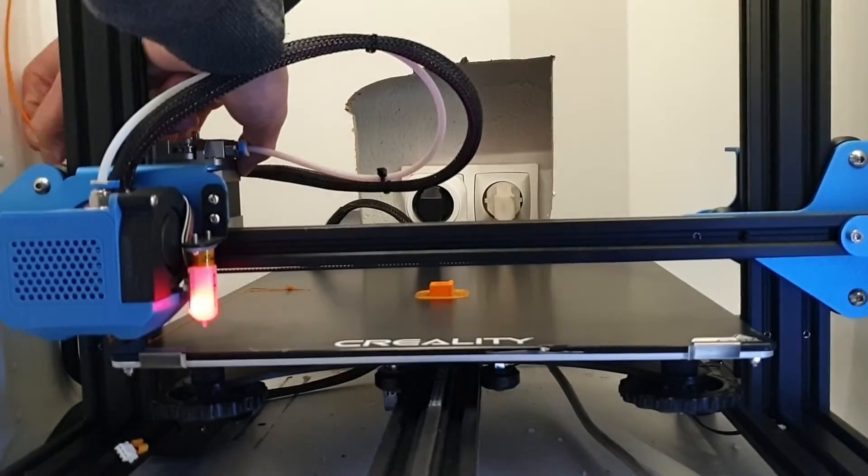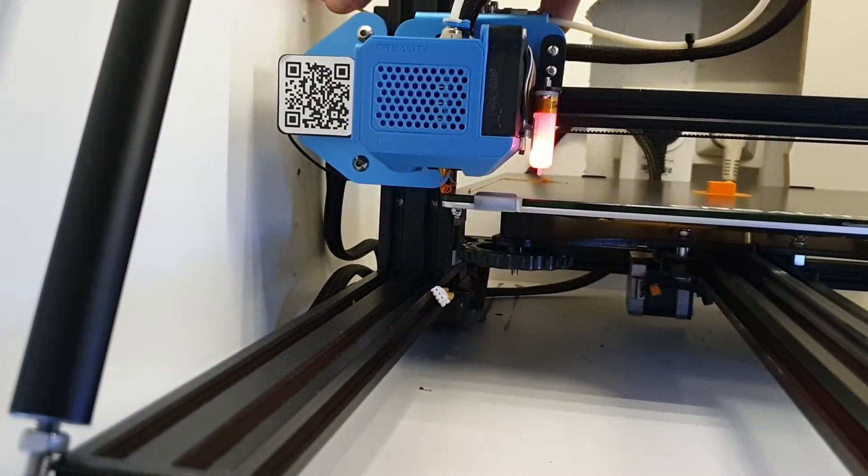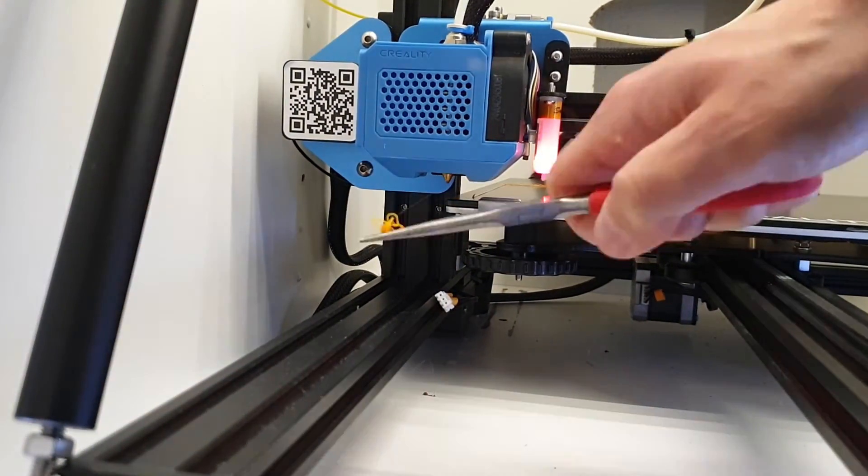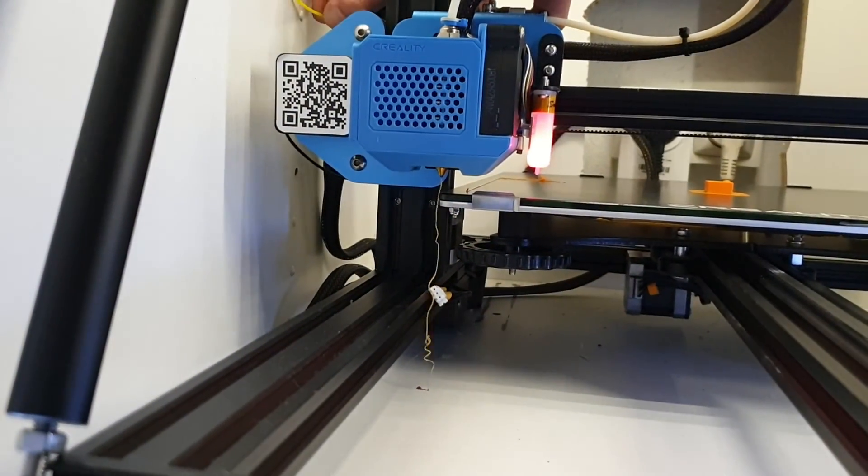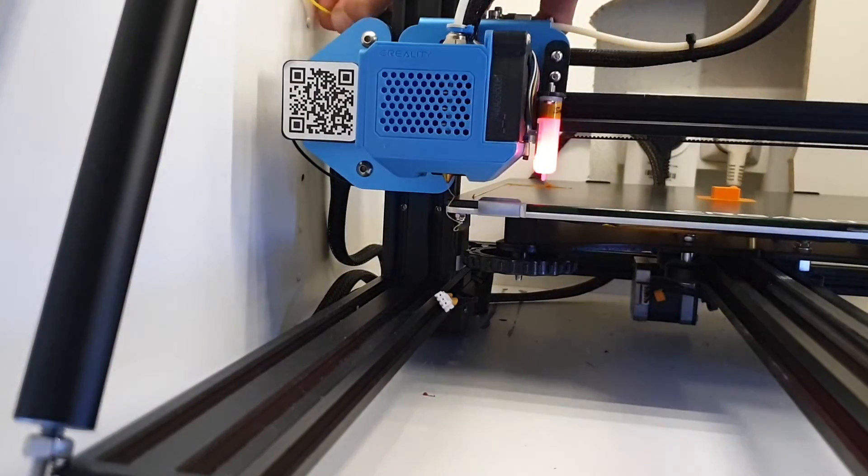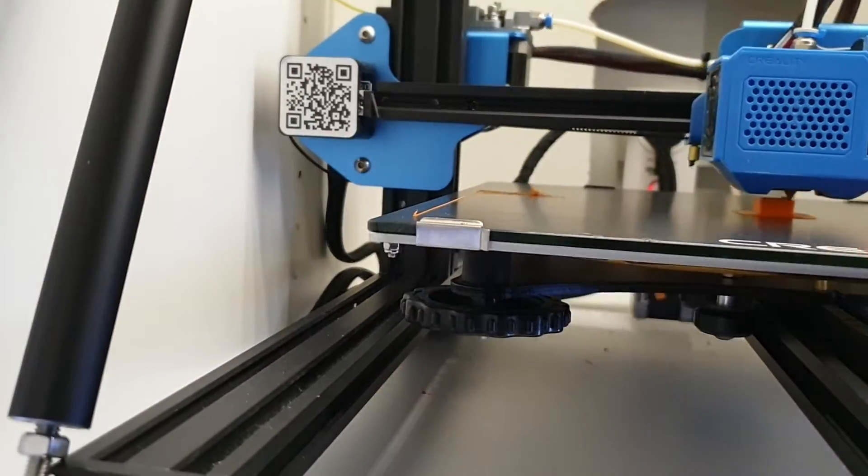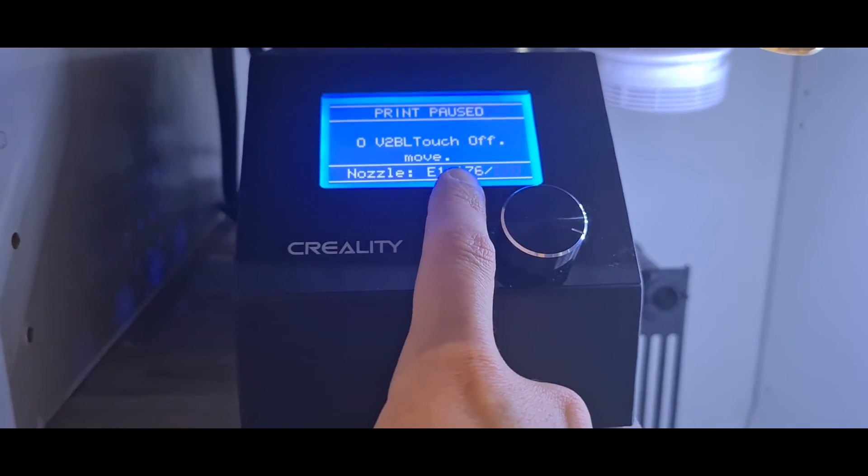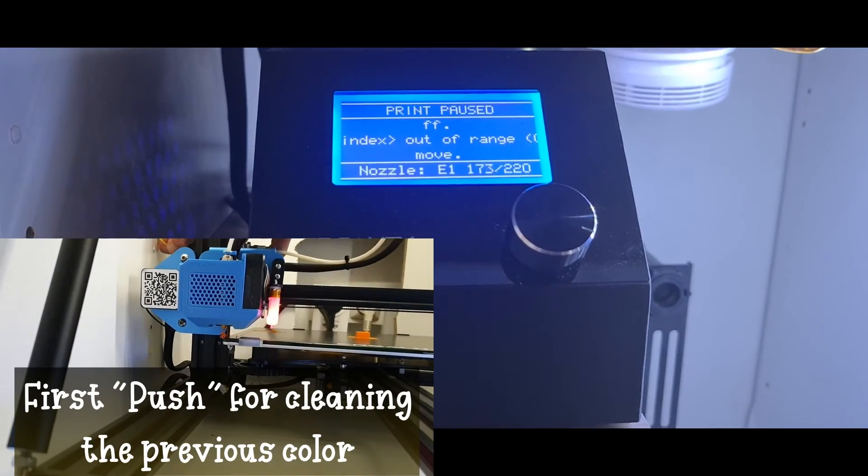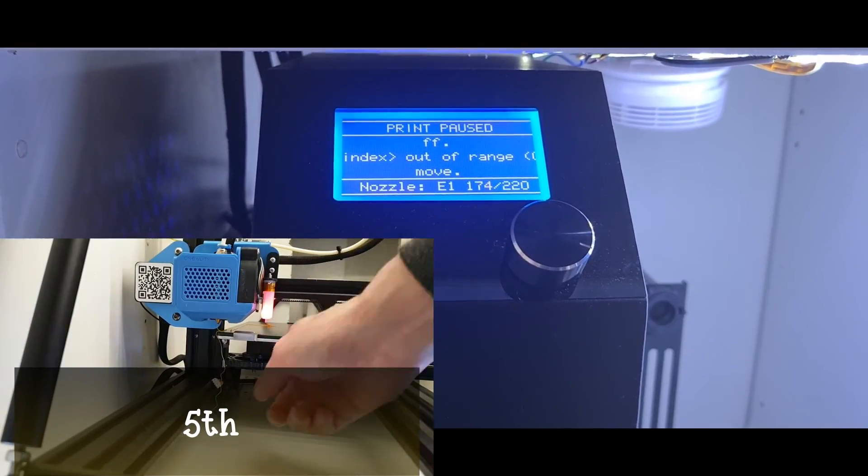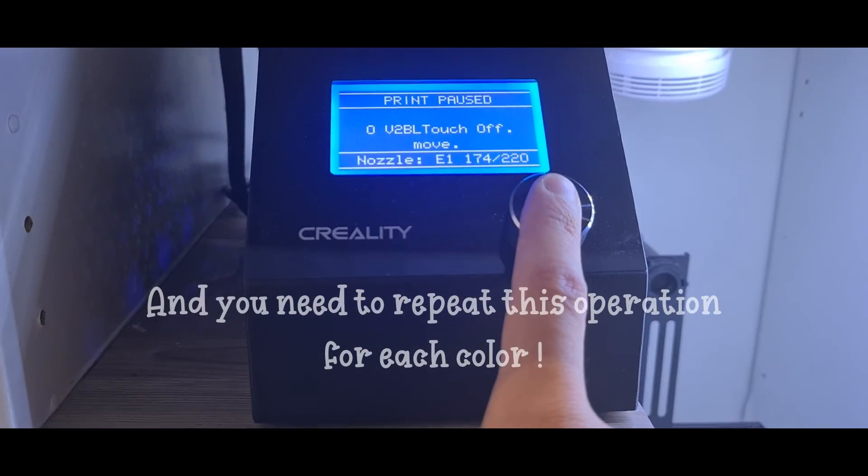The first change of filament was not so easy and of course I knew it but we have a little mix of colors because you cannot have a perfect clean extruder when you are changing the filament so quickly. When you are changing a filament you need a high temperature but the problem is that the printer is cooling the nozzle after only a few seconds so you don't have enough time to extrude all the previous color. So you have to push the button in order to have the higher temperature. You have few seconds to do it and then the temperature will go lower. So you have to push the button again.